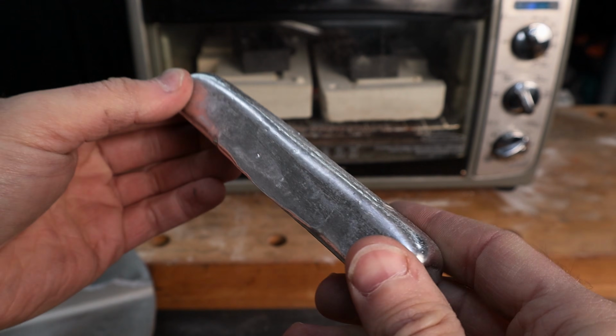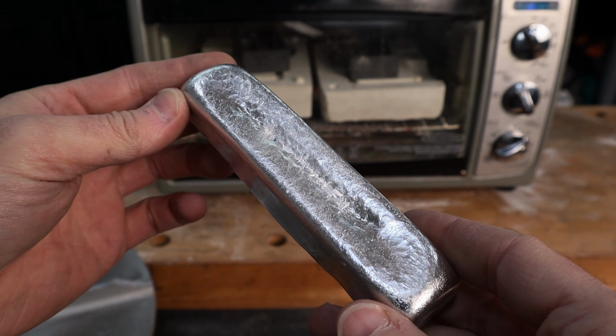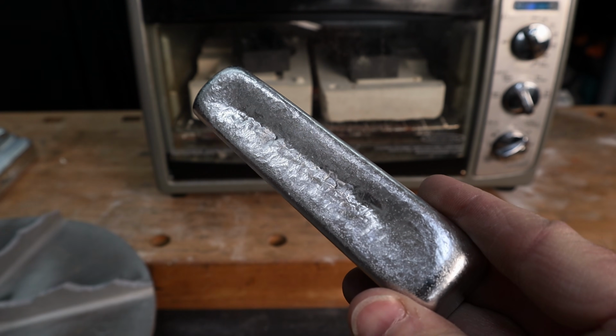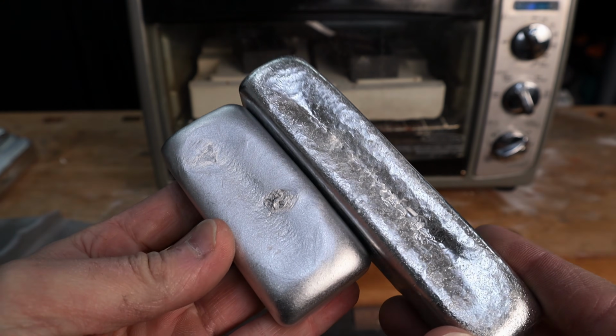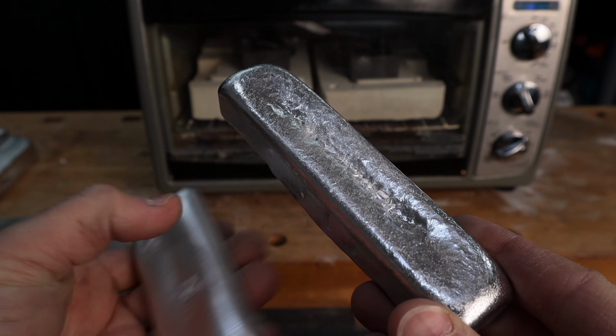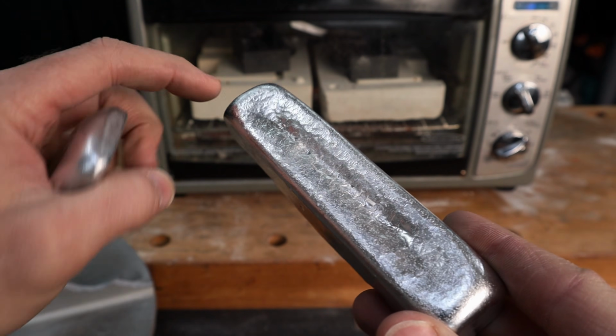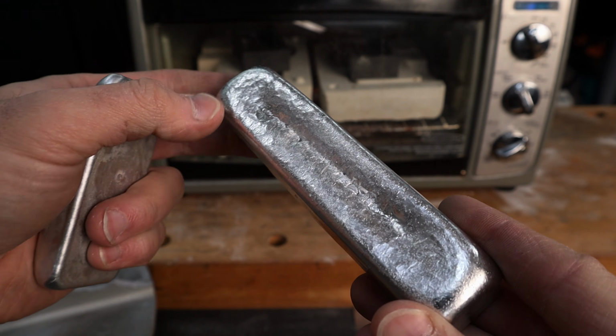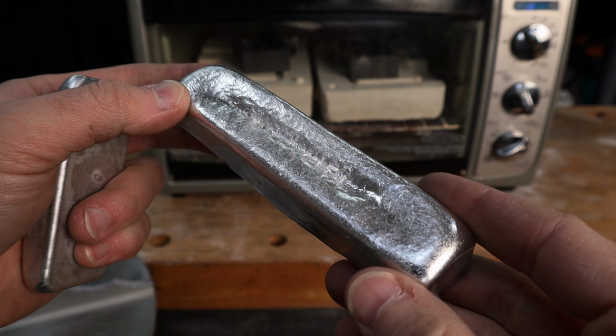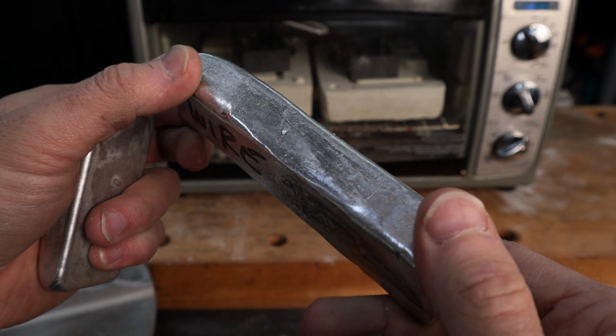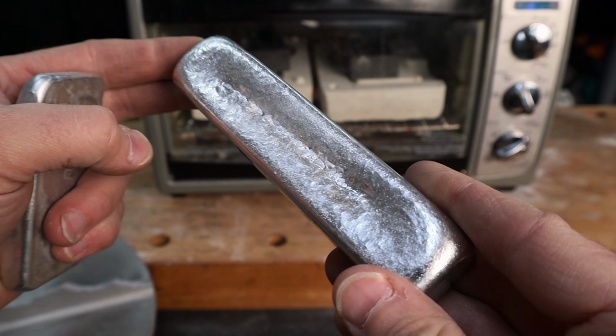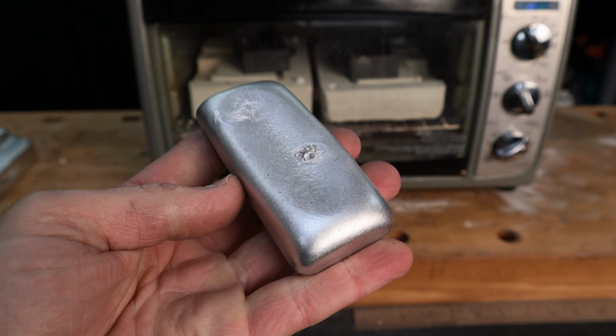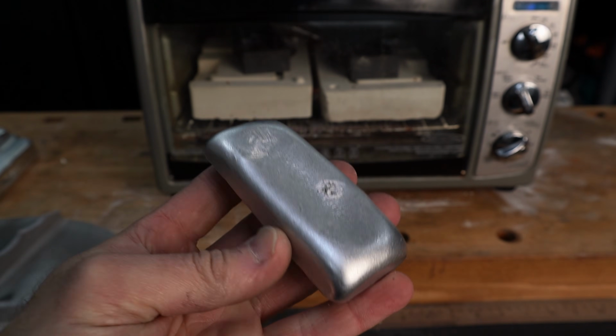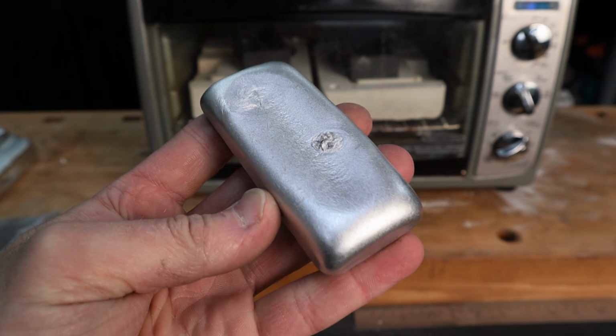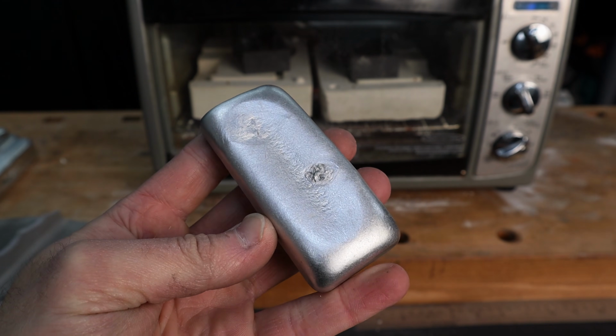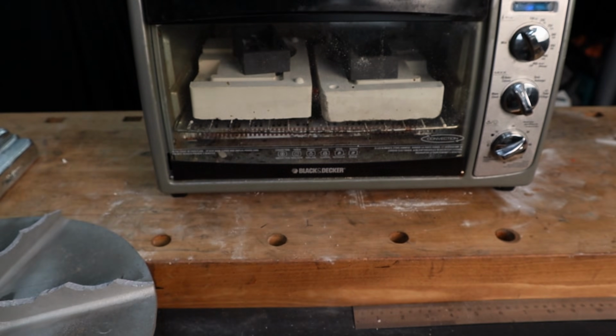So kind of a dull surface finish, a little bit of a depression in the center there. I melted down some aluminum wire to compare, and this is what it produced. A completely different surface finish. You can see it's very shiny in comparison to the casting material. And also we have this huge depression in the center, kind of indicating that this material shrinks quite a bit more when it's cooling. So I don't want to use what I melted down from wire. I want to use what we had from castings because that's what it's intended for. So it should work well to give us the best chance of success on our castings.